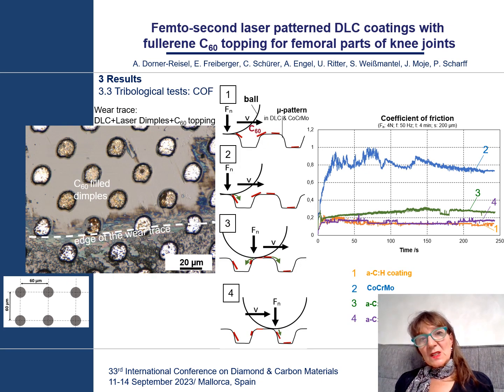Let's have a look inside the wear trace now. The dimples seem to be filled with C60. Apparently the zirconia ball did push the C60 needles inside the dimple during the movement. They are removed from the tribological loading zone and the coefficient of friction is reduced again. Also, a retarded setting free of the C60 can be expected in such a case.